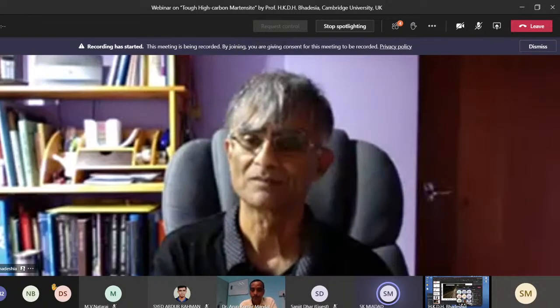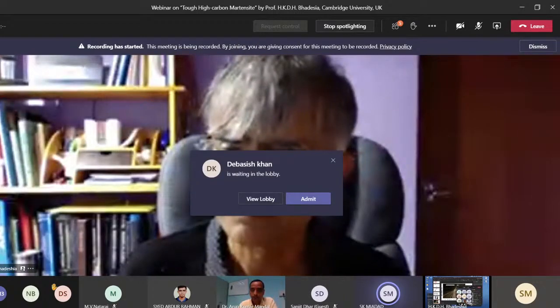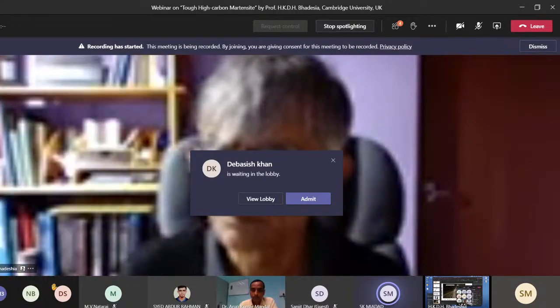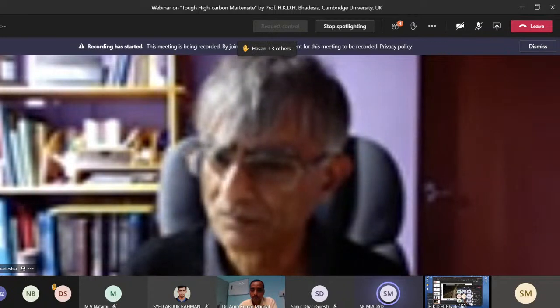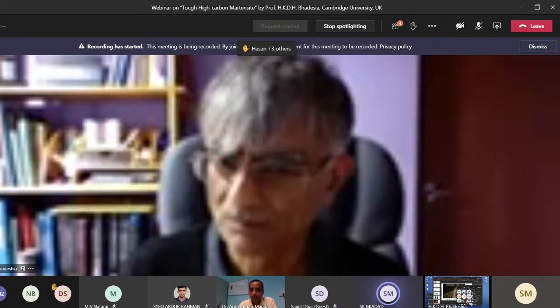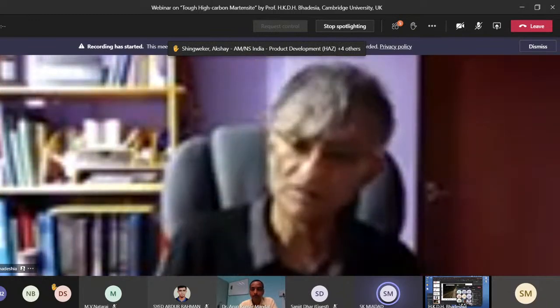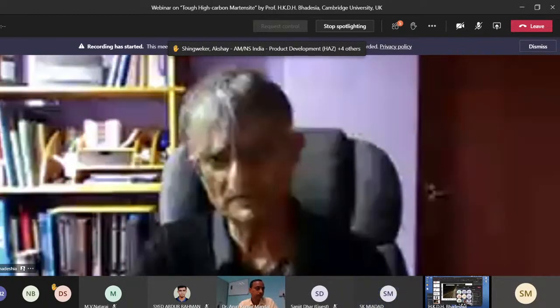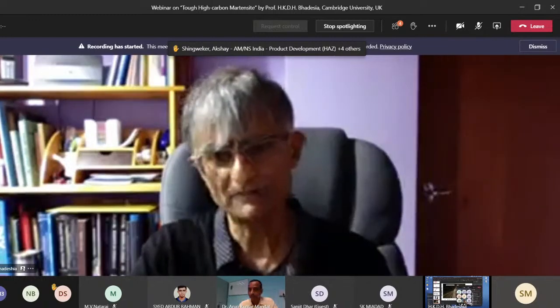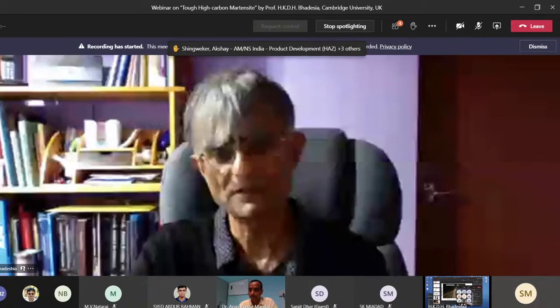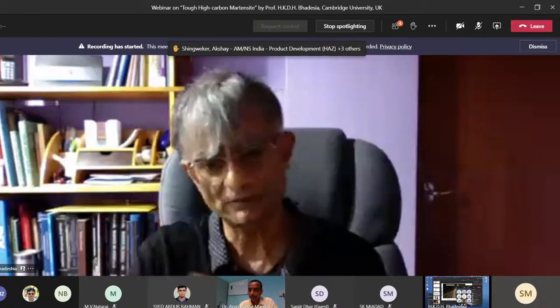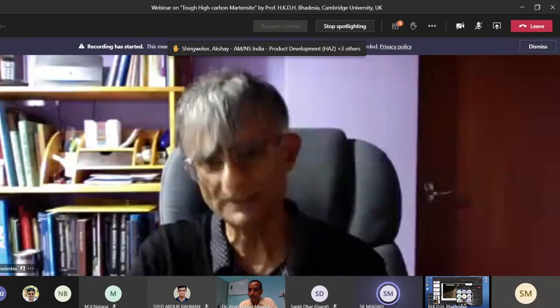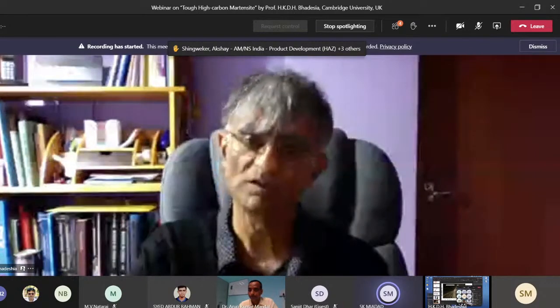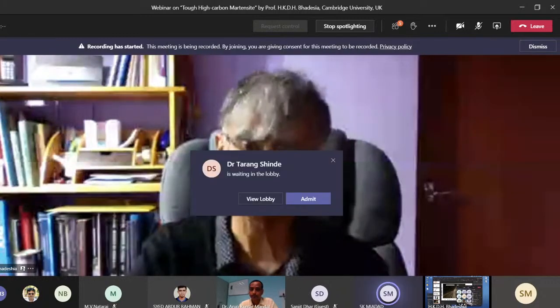Dr. Bhadesia, sir, in your slide number 36, you mentioned that fine untempered high carbon martensite is ductile, strong, and easily weldable. How is it possible? Is it due to fine structure or something? Yes. So in Tata Steel, they've used laser welding, arc welding, and so on. And in all cases, they can achieve a crack-free region in the heat affected zone. Because don't forget, we also have microalloying additions of vanadium in there. So we don't get a very coarse prior austenite grain size in the heat affected zone, and that's why we don't get the cracking.